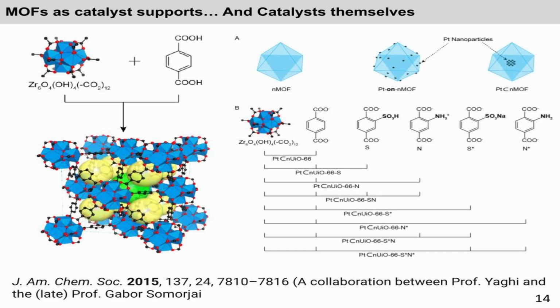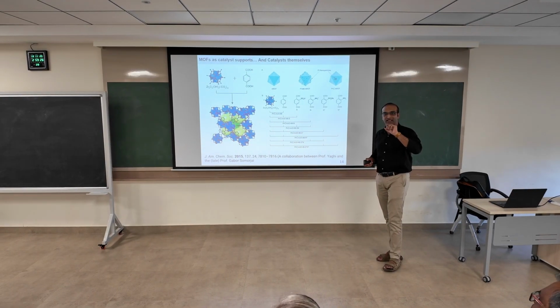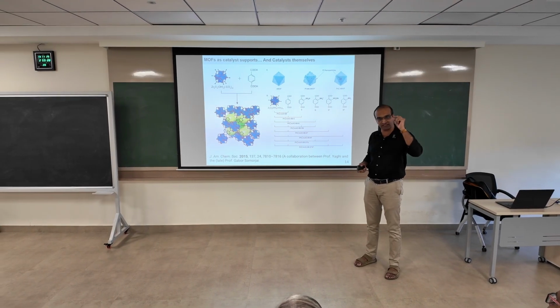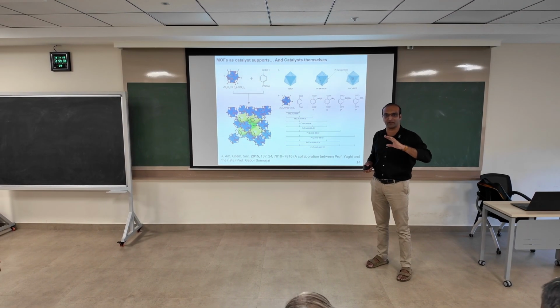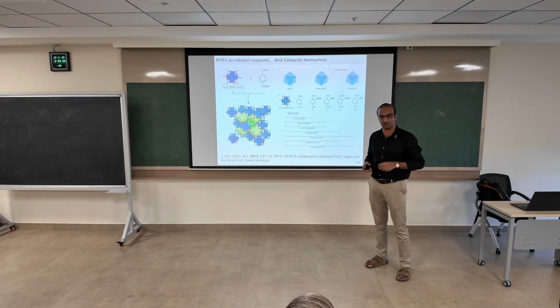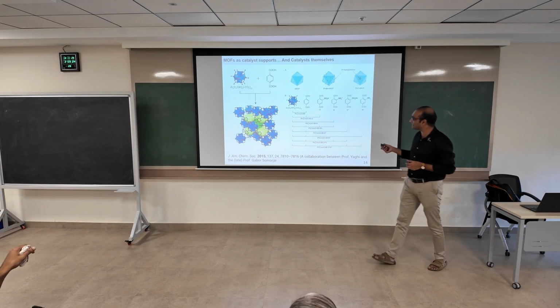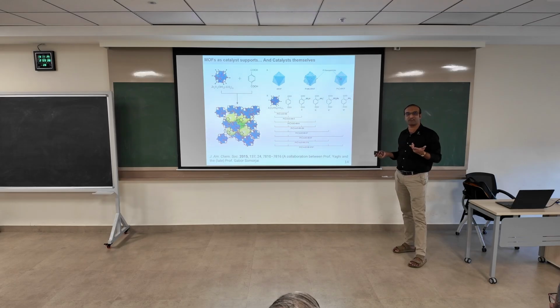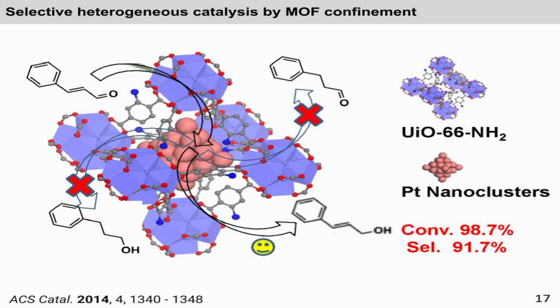when you have these particular things, it takes part in the catalysis. It acts as a co-catalyst along with the platinum nanoparticle, and forces the adsorption of the incoming substrate in a particular way so that only a certain product can come out. So by changing the acidity, they showed that you can get different kinds of products. Yeah, so this is the work we published.